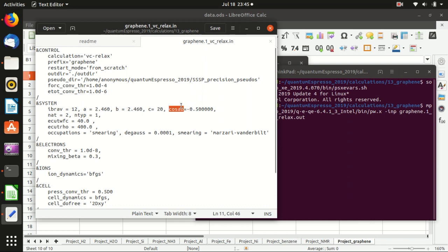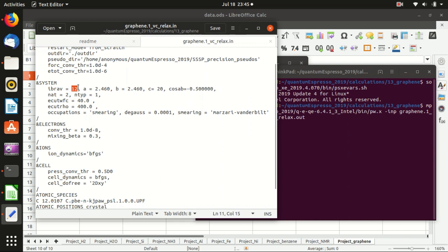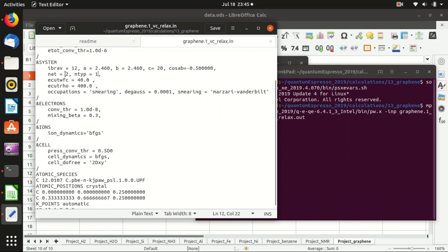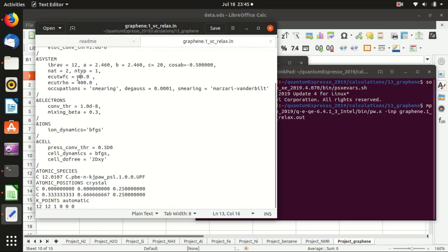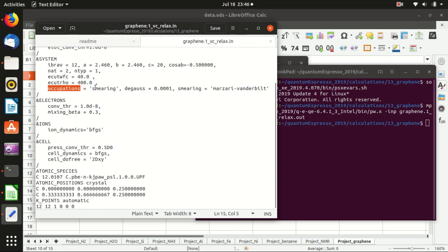This basically defines a 2D lattice with a very large c (z) spacing. The angle between a and c, and between b and c, are both 90 degrees — that is implicit in the definition of ibrav=12. We have two atoms per lattice cell and one type of atom. Note that we use an ultrasoft pseudopotential file, so ecutrho should be much larger than ecutwfc — more or less eight times, or even more than 10 times. Here we use 10 times for a more precise result.